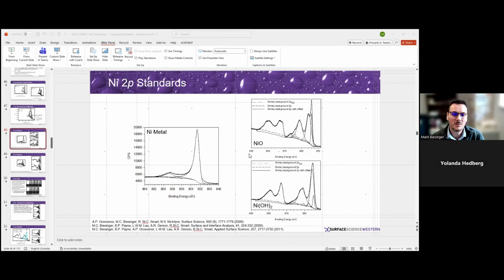I'm not familiar with CasaXPS. What do you use for fitting asymmetric metallic core levels? It's not a combination of Gaussian Lorentzian. Different software is going to have different functions to fit this asymmetric peak. We use CasaXPS. There are other ones that are available. There's different ways of calculating and modeling that asymmetry. Some of them are better than others. An older model would actually model the area under the peak, but it would carry on up. And so you get an over-exaggeration of the area under the peak. And so then they use these truncated models, which would stop after a certain binding energy. And then there's these new models that more accurately fit this area under the peak. So it's really just a math game, and it depends on who the developer is.